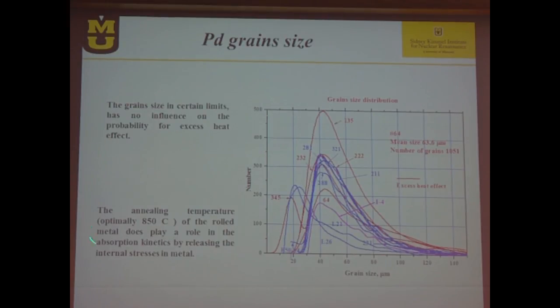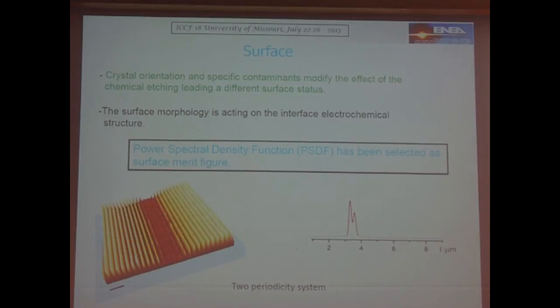But we know that by annealing, we are releasing stresses, we are making the process of loading of deuterium or hydrogen into the lattice easier, and it's easier to get to a high loading ratio. So it's important to get high loadings, but it's not promising a high reproducibility rate. So then, as you know, crystal orientation and specific contaminants are very important, and I'll speak about that a little bit later.